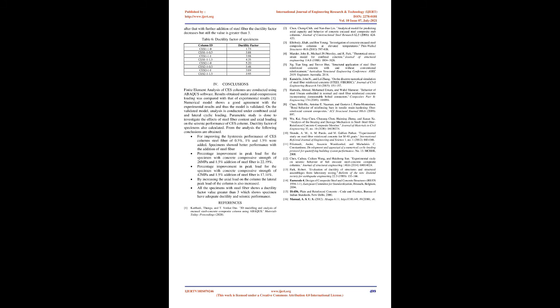For improving the hysteresis performance of CES column, steel fiber of 0.5%, 1%, and 1.5% were added. Specimens showed better performance with the addition of steel fiber. Percentage improvement in peak load for the specimen with concrete compressive strength of 26 MPa and 1.5% addition of steel fiber is 22.19%. Percentage improvement in peak load for the specimen with concrete compressive strength of 42 MPa and 1.5% addition of steel fiber is 17.14%.